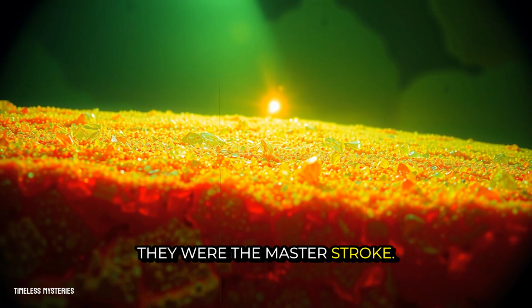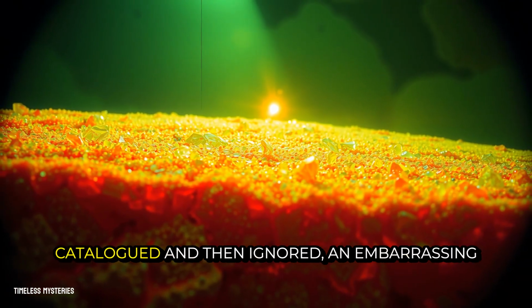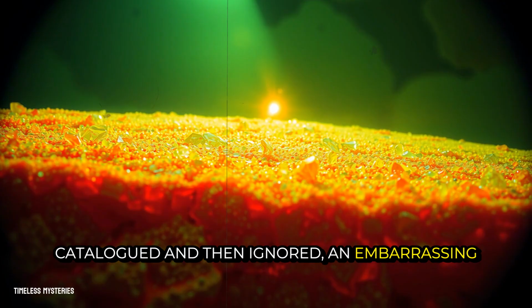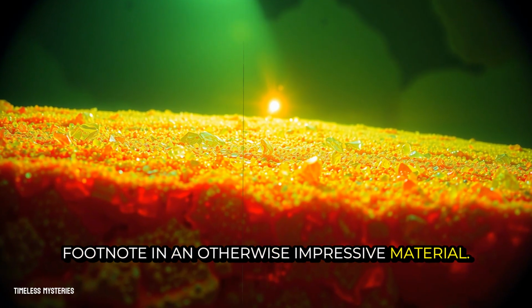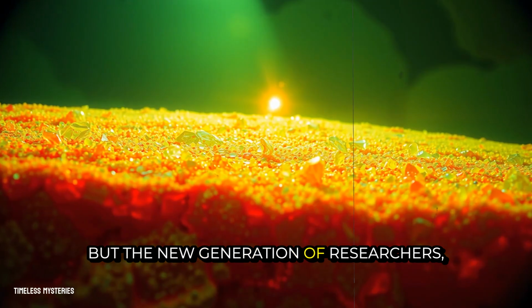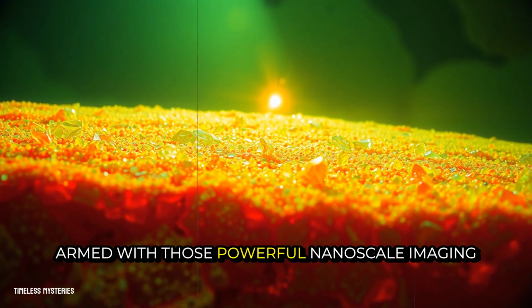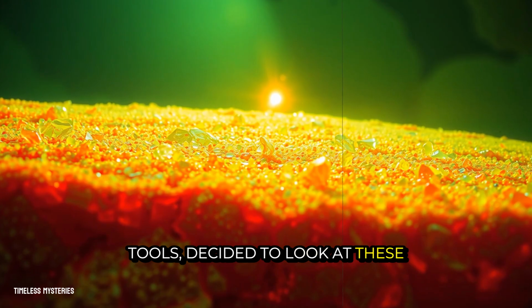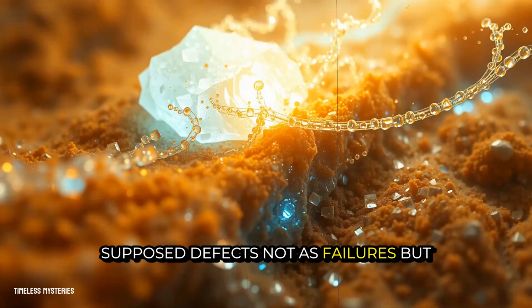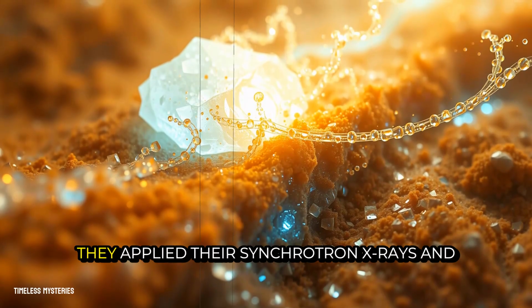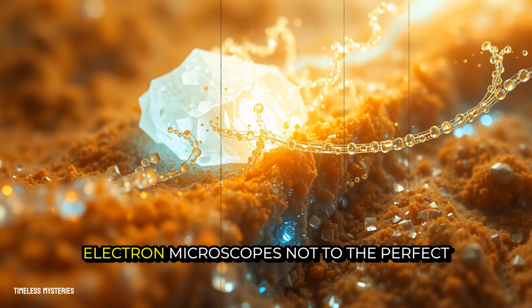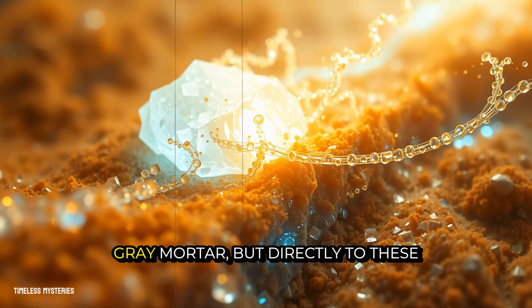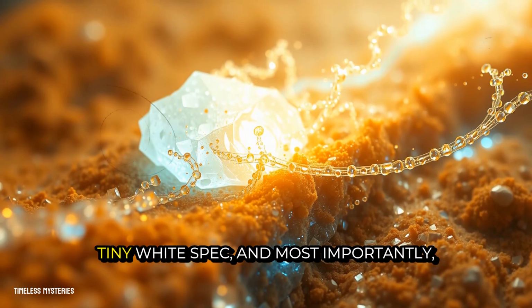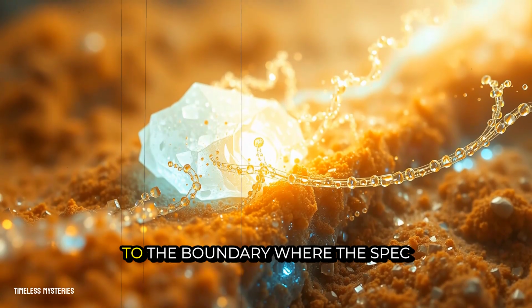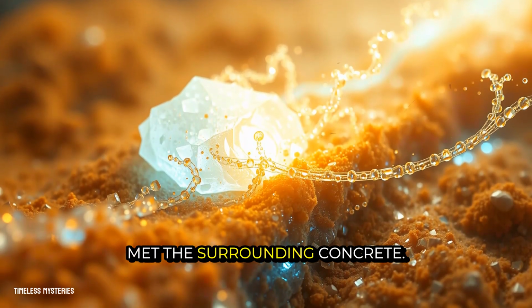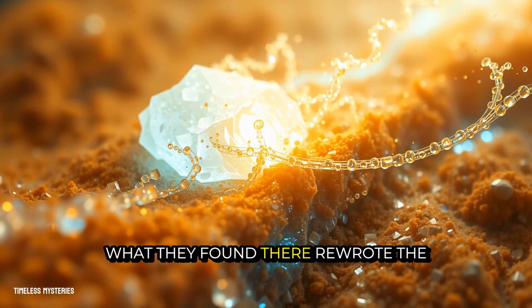They were the masterstroke. For decades, the lime clasts were catalogued and then ignored, an embarrassing footnote in an otherwise impressive material. But the new generation of researchers, armed with those powerful nanoscale imaging tools, decided to look at these supposed defects not as failures, but as features. They applied their synchrotron X-rays and electron microscopes not to the perfect gray mortar, but directly to these tiny white specks, and most importantly, to the boundary where the speck met the surrounding concrete. What they found there rewrote the recipe.